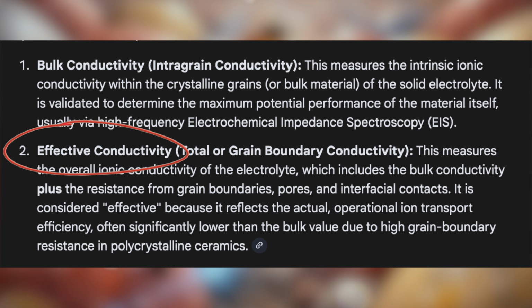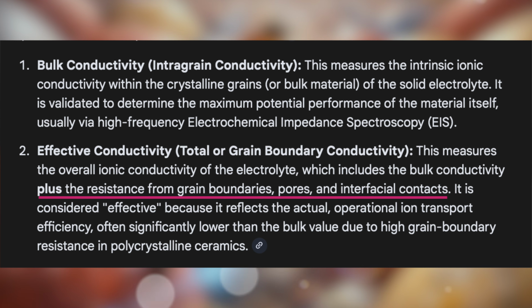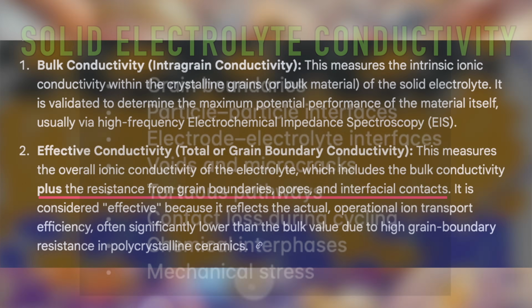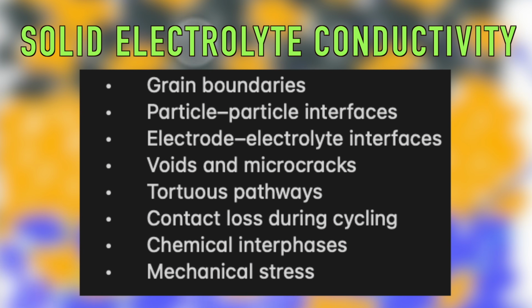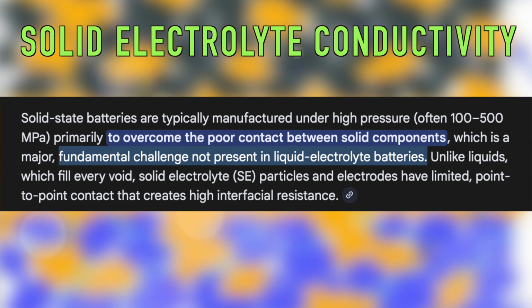Bulk conductivity is, can ions move through this material if nothing goes wrong? The real world stuff, or effective conductivity, answers the real question. Can ions move through this once everything goes wrong at the same time? A solid electrolyte introduces a ton of new problems in the real world, which is that effective conductivity. They include grain boundaries, particle-to-particle interfaces, electrode-to-electrolyte interfaces, voids and microcracks, tortuous pathways, contact loss during cycling, chemical interphases, and mechanical stress. And one of the only methods we know to use to solve most of these problems is high pressure. More on that in a second.